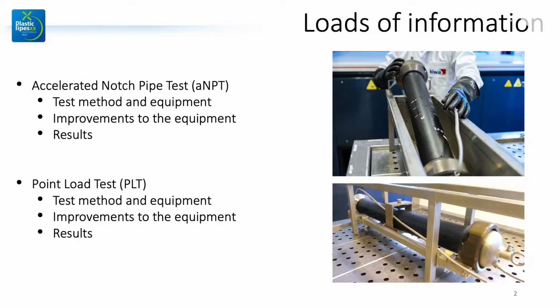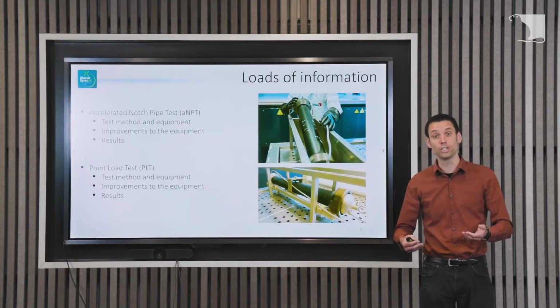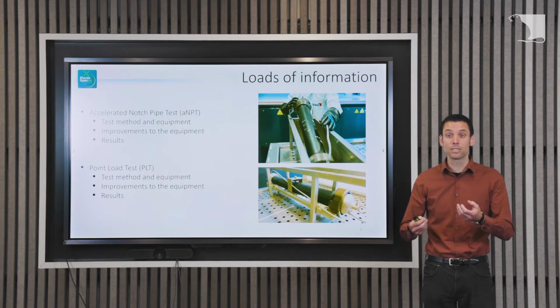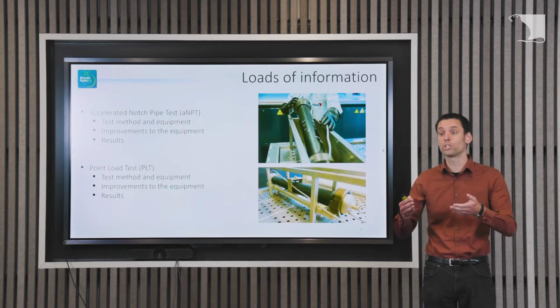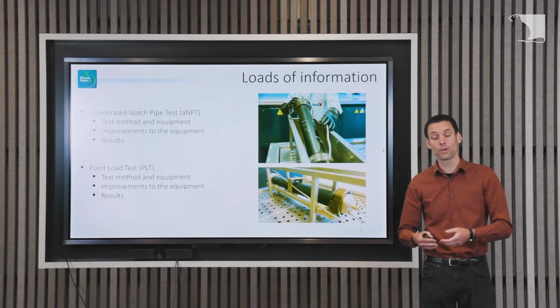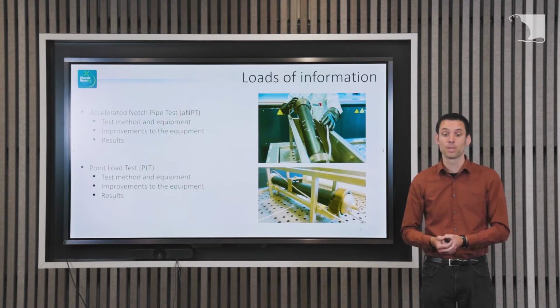And well, like I said, it's about two pipe tests. The first one is the accelerated notched pipe test. The accelerated notched pipe test is to measure the pipe's resistance against surface damage, for instance because of a scratch due to careless installation. And this scratch can, of course, grow further. This can crack the pipe eventually. So the test measures the resistance of the material against it.